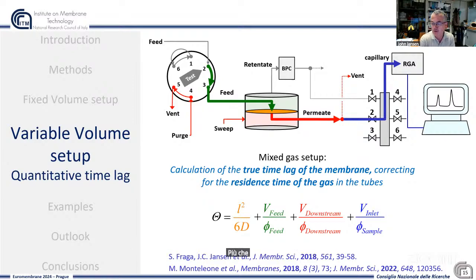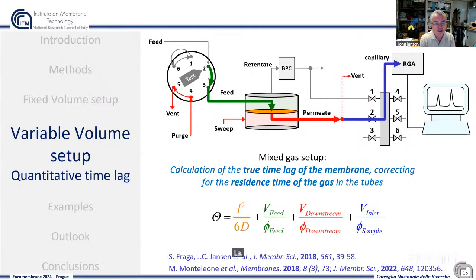While if you have a good system and you optimize it and you have a sensitive mass spectrometer, it can take points per second. So we are a little bit slower, but still we can measure every few seconds a point. And that means that transient phenomena that take a minute or so, which are not uncommon, we see that over the whole curvature of the signal. So it's a really powerful method.